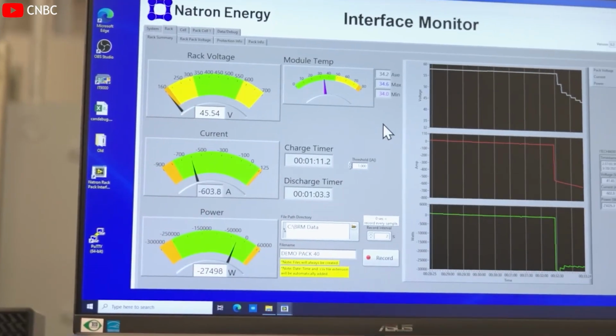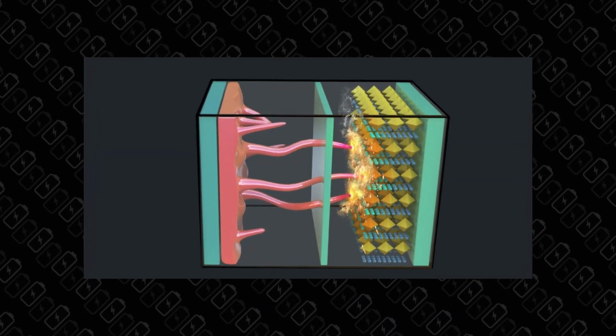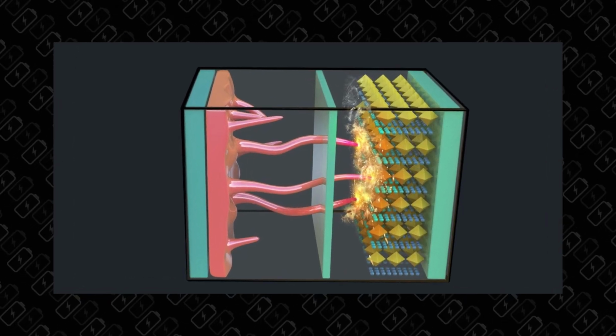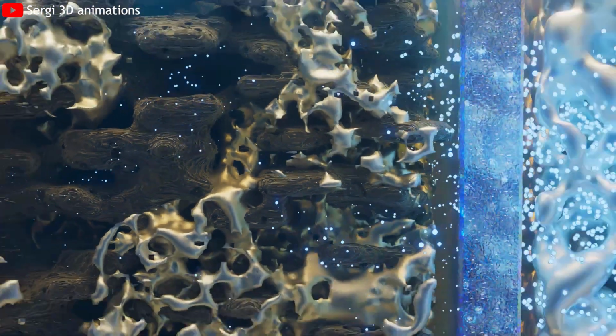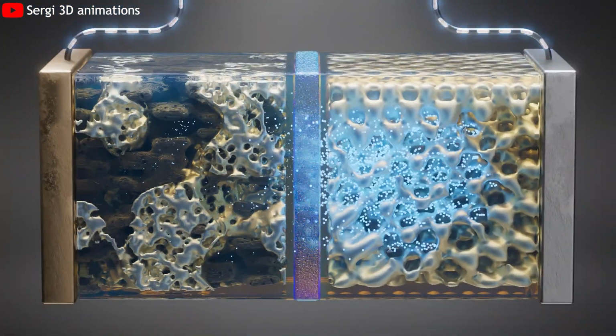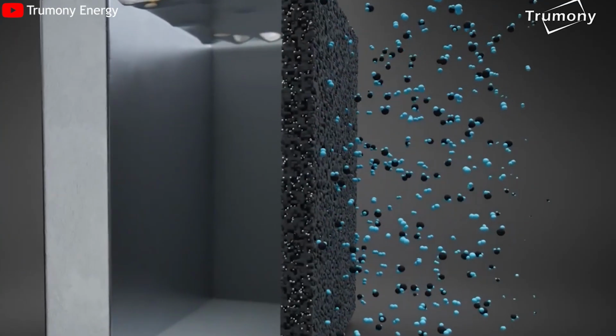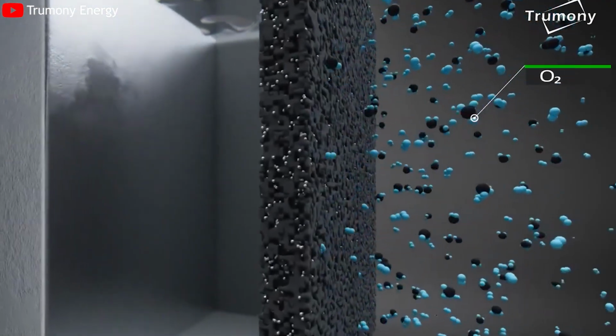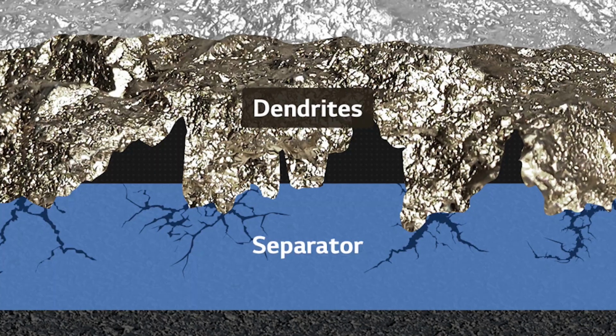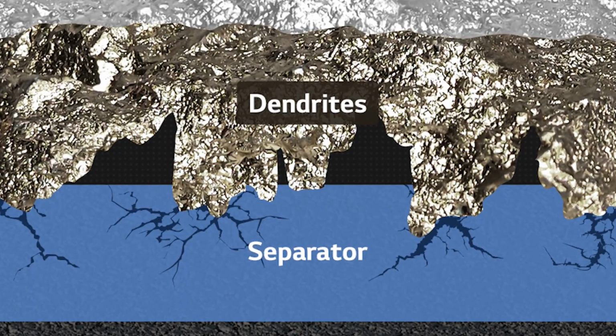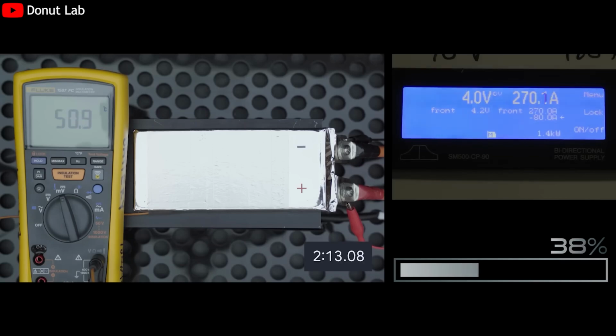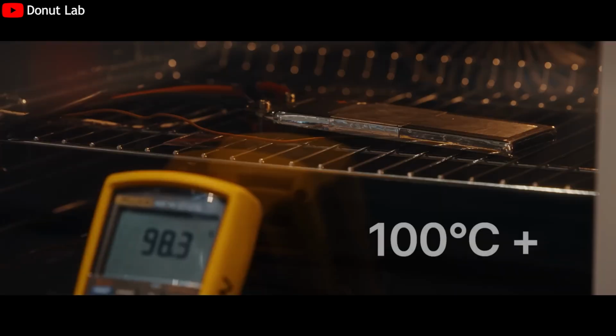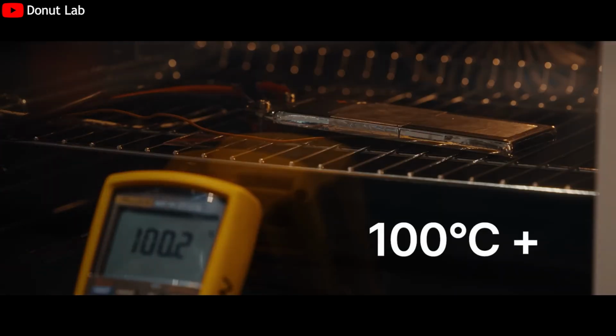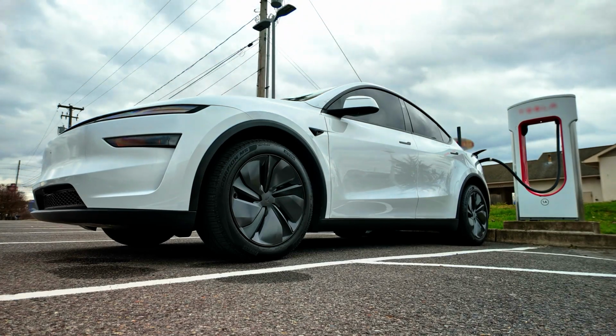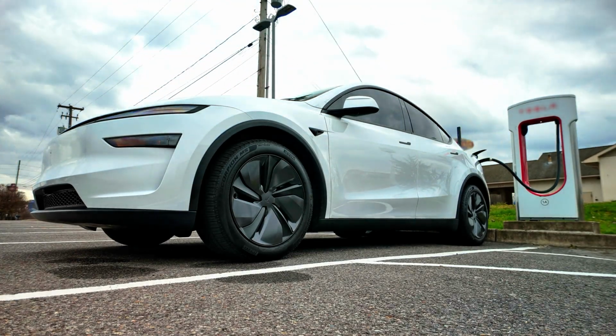Pressure builds up at the interface. Contrary to marketing claims, dendrites do not need to be harder than ceramic to break it. They simply grow through grain boundaries, the microscopic seams between crystals, or propagate through pre-existing microcracks. The so-called solid barrier is not a wall. It behaves more like a sieve. When dendrites penetrate along grain boundaries and reach the cathode, the battery short circuits. Startups conceal this by testing at low current densities, charging over 3 hours instead of 15 minutes, or by heating the cell to 60 degrees Celsius to soften the lithium. But try telling consumers they must preheat their vehicle for an hour before fast charging.